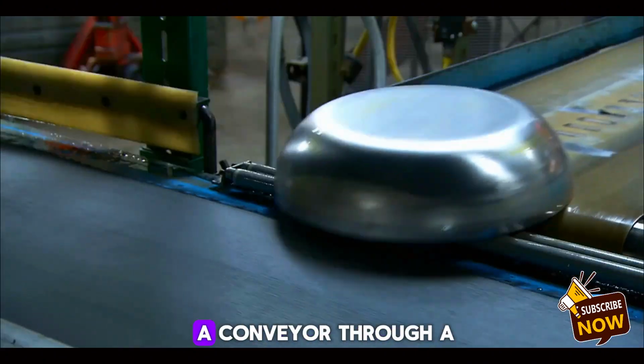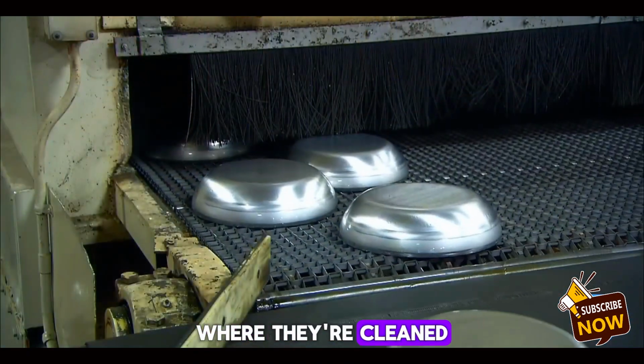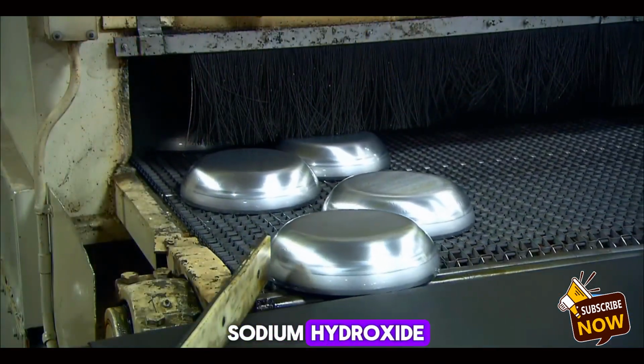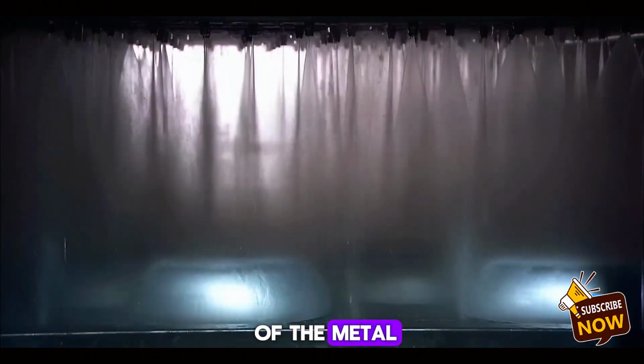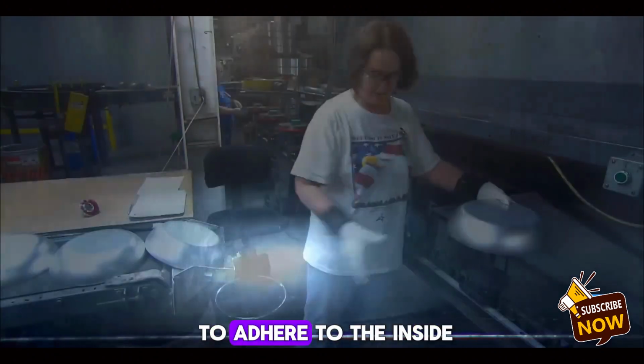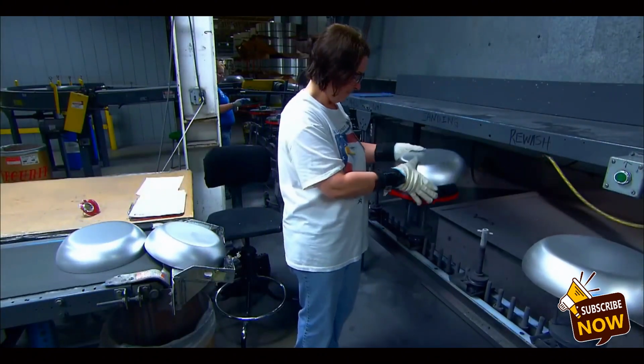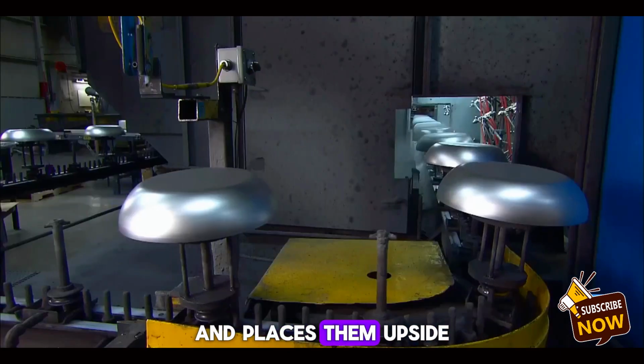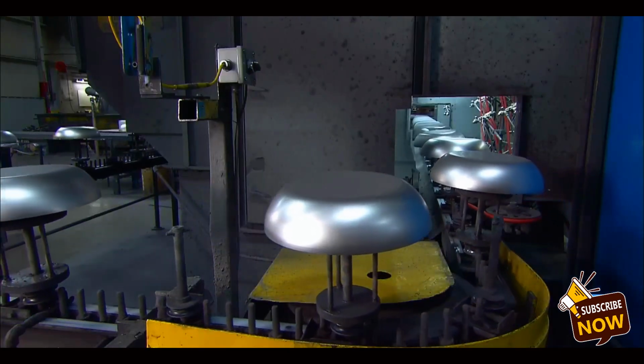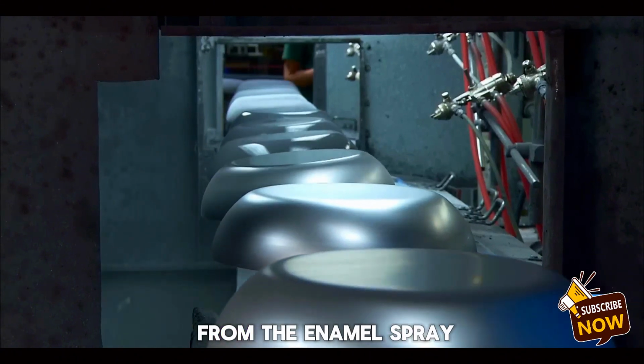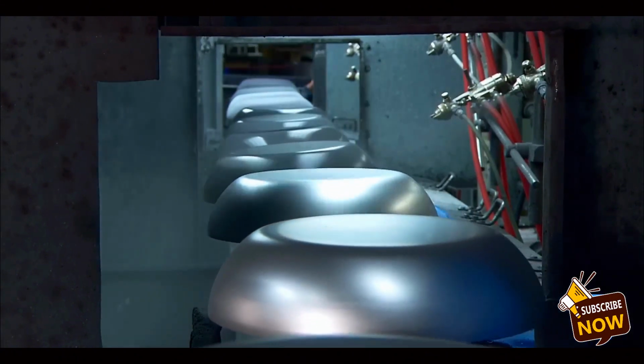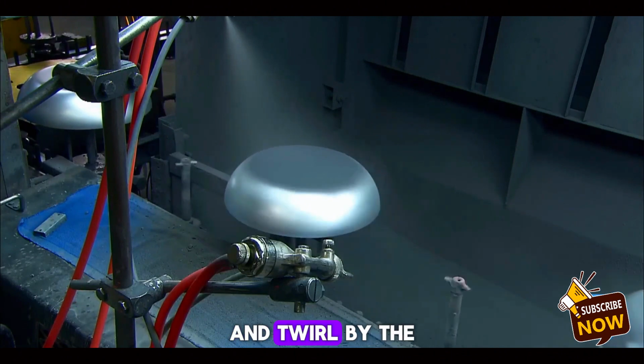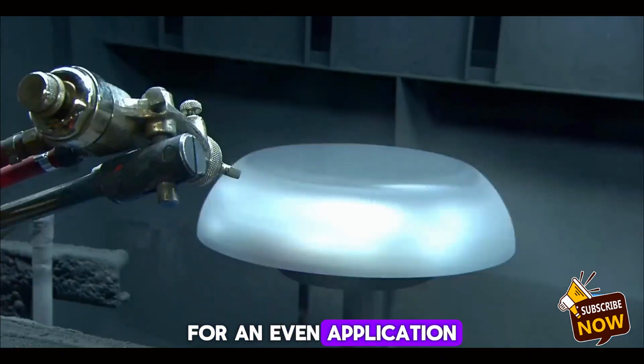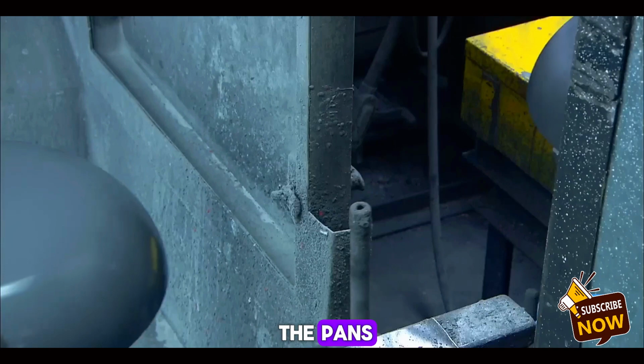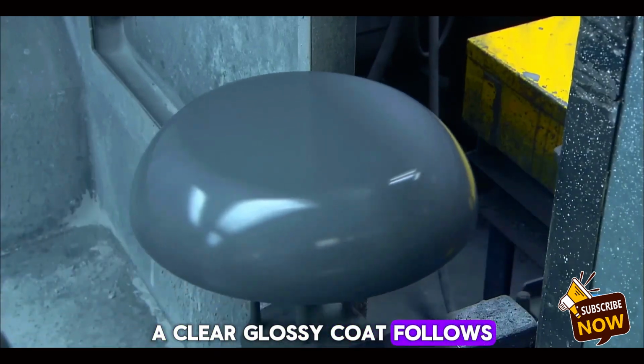The pans now ride a conveyor through a washing station, where they're cleaned and then treated with sodium hydroxide. This opens the pores of the metal to allow an enamel coating to stick to the outside and the non-stick finish to adhere to the inside. A worker inspects the pans and places them upside down on spray fixtures. It's a tight fit to shield the inside from the enamel spray that comes next. The pans spin on the fixtures and twirl by the spray nozzles for an even application of enamel to the exterior of the pans. A clear glossy coat follows.